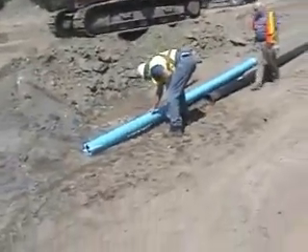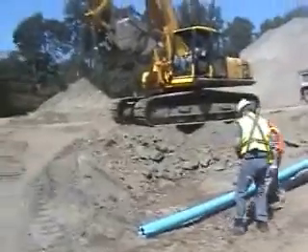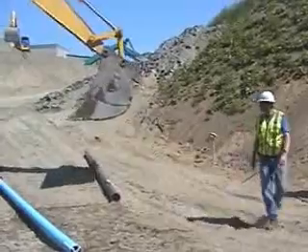The initial test involved hitting both pipes with a sledgehammer. The sledgehammer bounced off of the Bionax pipe without causing any damage. When the ductile iron was hit, the pipe became dented and the inner cement mortar lining broke off locally.